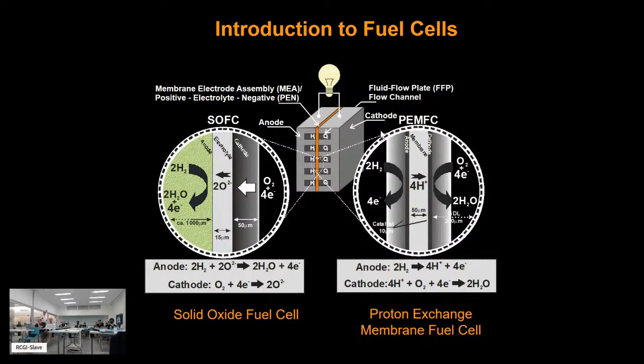These PEM devices generally have higher power density than the solid oxide ones. They run at lower temperatures and are faster to start up, so you tend to find these historically tailored for transport applications. The solid oxide devices run at temperature and produce steam, hot water, so they're good for applications where you want power and heat. And because they're hot, you can not only put hydrogen in, but you can put carbon monoxide and other fuels in, so they have much more fuel flexibility. Whereas the PEM devices use platinum-based catalysts, and those are poisoned by things like carbon monoxide and other impurities in the fuel. So that makes them more difficult to use.